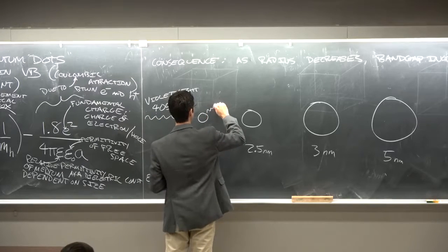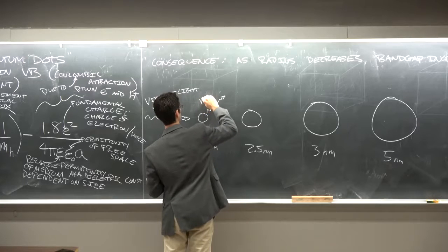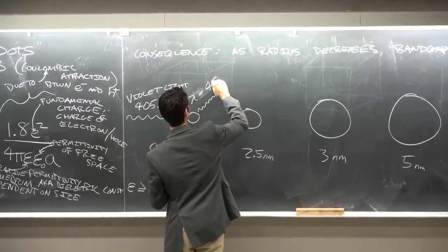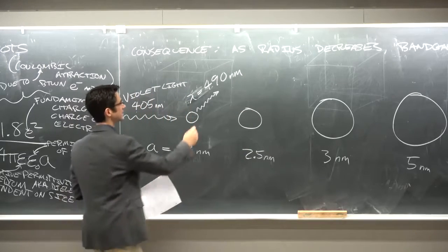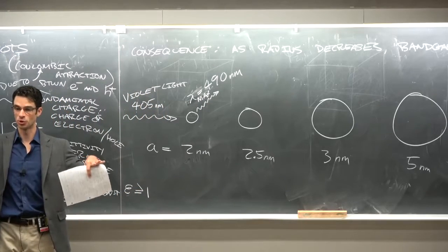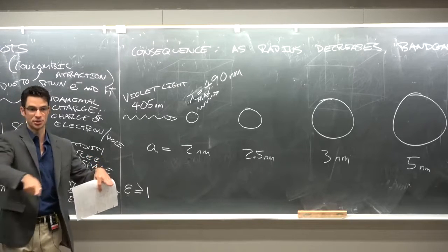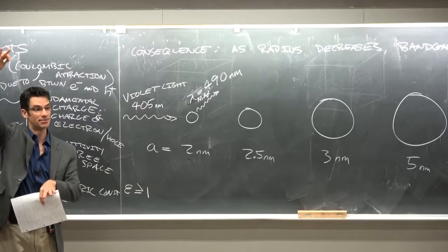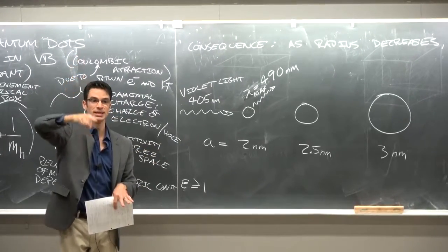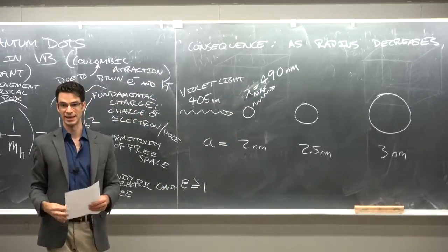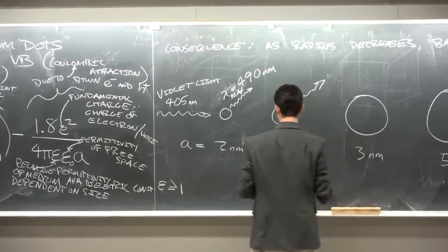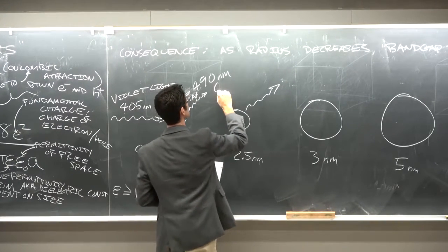So what this does is it emits a photon with a wavelength of 490 nanometers. And this is the lambda max of emission. So if you have a plot of absorption versus wavelength, it's not going to be a straight line because you have a density of states on either side of the band edge. It's going to be a lazy peak, but the peak will be about 490 nanometers. And this is for cadmium selenide quantum dots. By the way, 490 nanometers is something like blue-green.